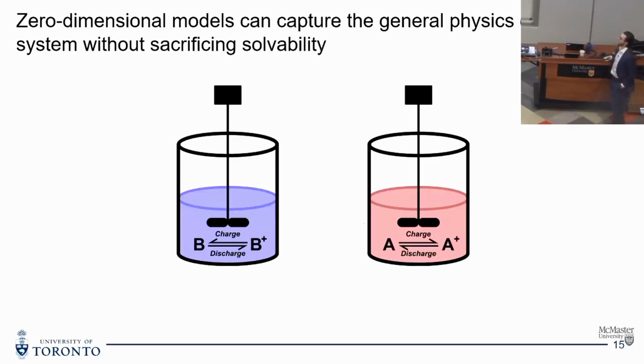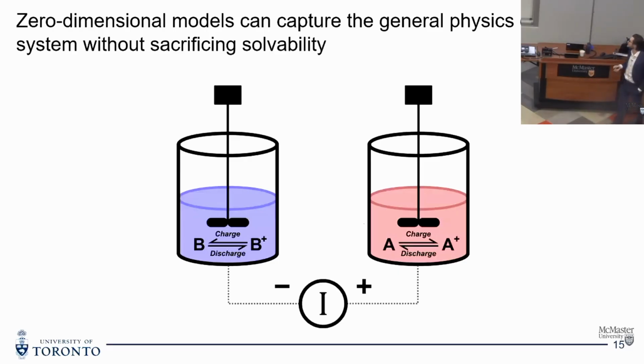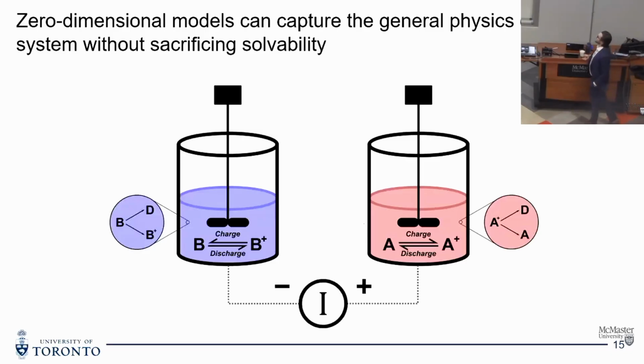We can then incorporate certain failure modes. So we have our applied current. We can think of how these electrolytes decay. Here I'm showing this generally as some decay process where our charged species goes to some decayed product D, or it can go back to our original uncharged state via a process called self-discharge. And then we also have crossover of our species through the membrane. So if our membrane's not perfectly selective, then we might have B crossing over to the A side, A crossing over to the B side.